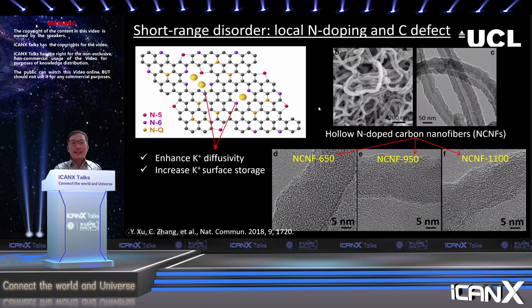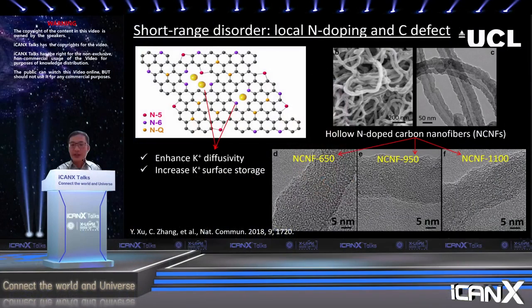What we did experimentally is to use a very simple polymerization method to obtain the polypyrrole at first, and we carbonized the polymer at different high temperatures in order to control the degree of carbonization of the material. The degree of carbonization also determines the types of nitrogen doping, therefore the level of the carbon defects. We were able to obtain the soft carbon materials by carbonizing the polymer at 650, 950, and 1100 degrees.